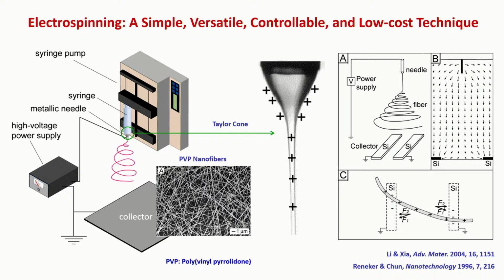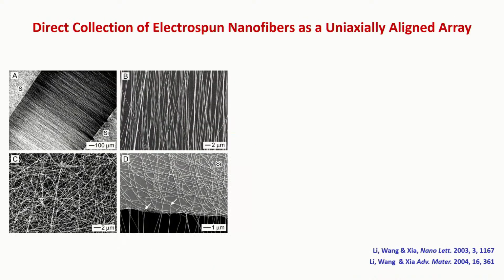And the idea is to use 2 electrodes to collect the fibers. So there is going to be an insulating gap. Across this gap, you are going to have fibers coming down to create a very strong stretching force, because these fibers are still charged. So they can induce opposite charges on these 2 electrodes. So you are going to induce a very strong stretching force, and the fibers will be aligned basically across this gap in these perpendicular directions.